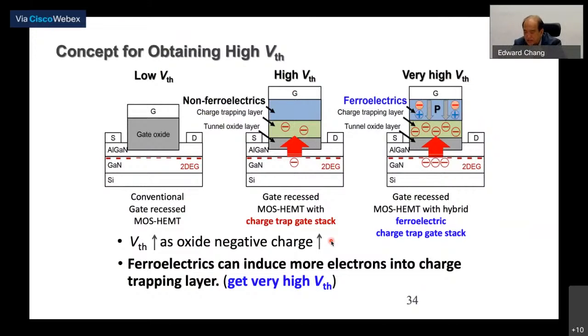This right-hand side structure is what we have. We have a tunneling oxide, and then a charge trapping oxide, and the tunneling oxide prevents the charge from going away, and on top of that you have a ferroelectric material to create an electric field. In that way, we can create an enhancement-mode device. That's what we call the ferroelectric charge trapping stack.